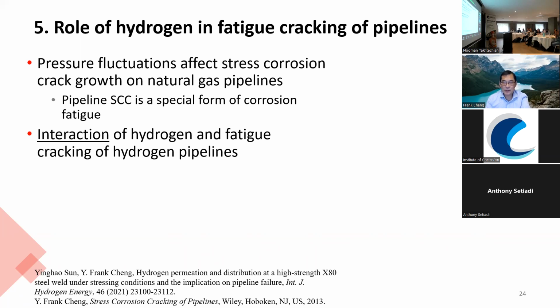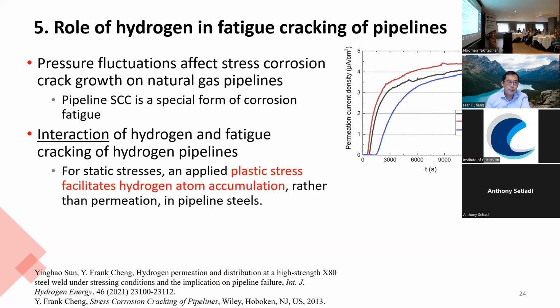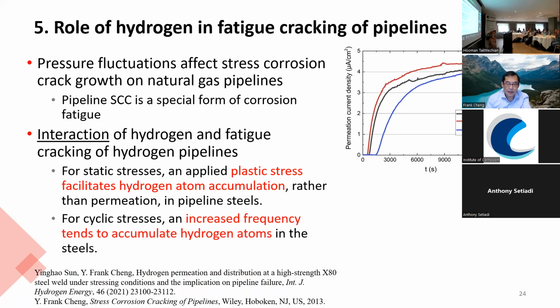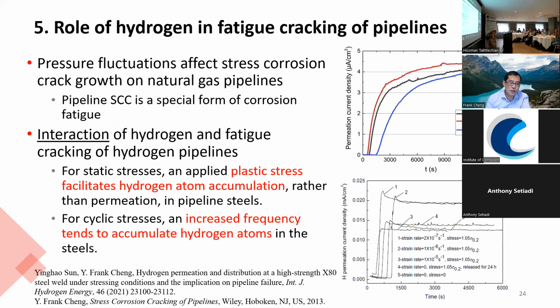The same thing, we will use the steel pipeline to carry hydrogen or hydrogen blended with natural gas. And the big concern is how hydrogen will influence fatigue cracking. So that's the interaction of hydrogen and fatigue, compared with static stress. You can see from these results that plastic stress can facilitate hydrogen atom accumulation, but not permeation. But if the stress is cyclical, such as pressure fluctuation, an increased frequency tends to accumulate hydrogen atoms in the steel.